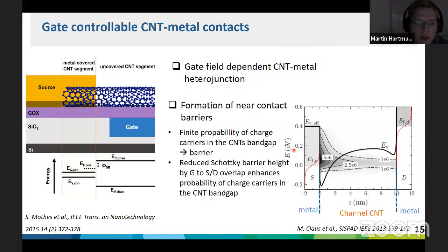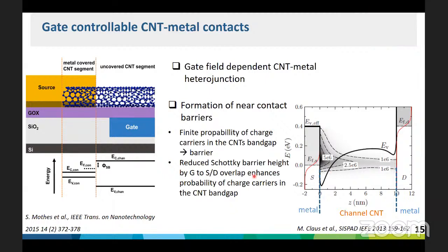The other explanation is near contact barriers. M. Claus et al. have shown that there is a finite probability for some charges to be within the band gap of the CNTs. This probability increases if you reduce the barrier between the CNTs and the metal contact. If you reduce the barrier, you have more of these charges within the band gap, which can again reduce your overall transconductance. So these are two ongoing theories why the transconductance is reduced.